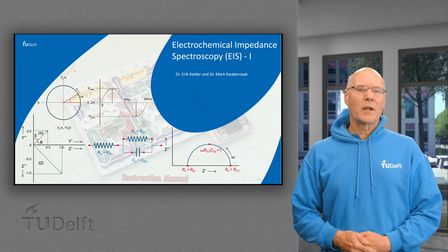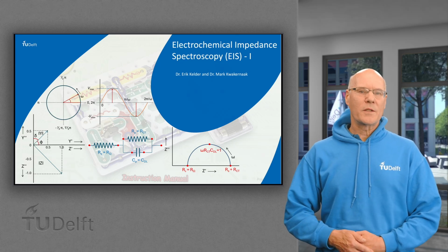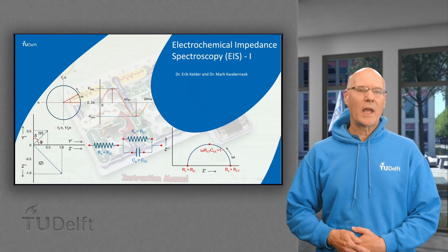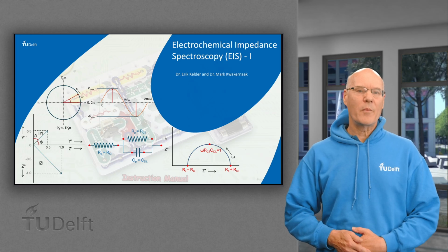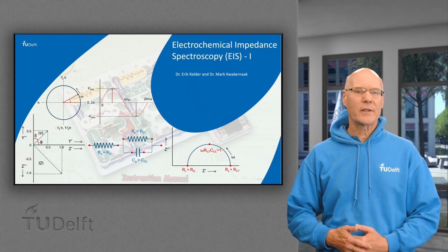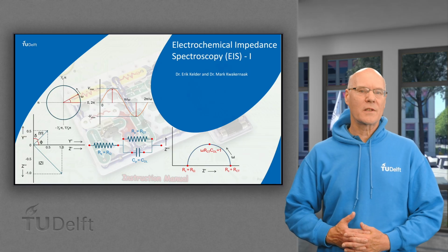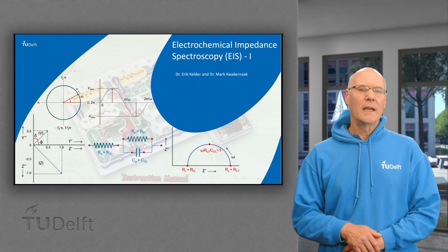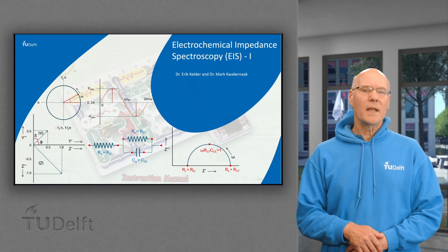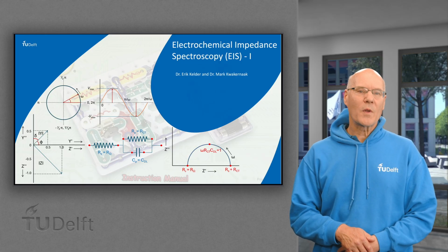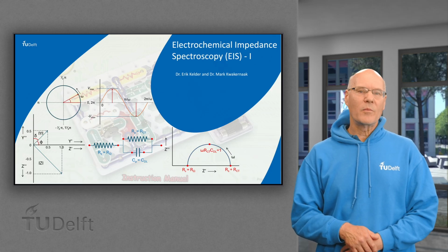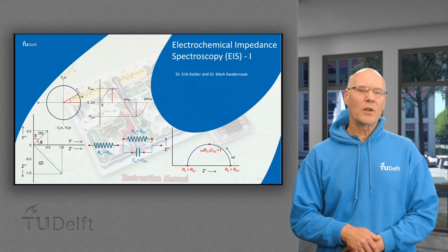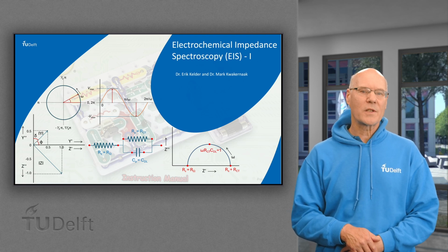Batteries operate under a current of electrons and ions, which migrate back and forth from the electrodes. Electric behavior, therefore, can be analyzed by measuring the resistance, or better, the alternating current resistance, the impedance. Since impedance measurements are carried out at a series of frequencies, they also reflect time constants. And because several mechanisms in the battery are time dependent, it is possible to deconvolute these mechanisms and processes by